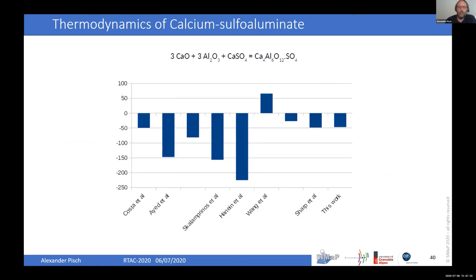And here, just to show you, you see the enthalpy of formation with respect to the reaction given above. And our calculation, which is on the right, is in very good agreement with an enthalpy of solution measurement by acid dissolution by Costa et al in the late 70s. But all the other subsequent data is much more negative and can now be discarded in the discussion. There was even some positive value which can also be discarded. So we can now really assure that the value should be in this ballpark and not like this.